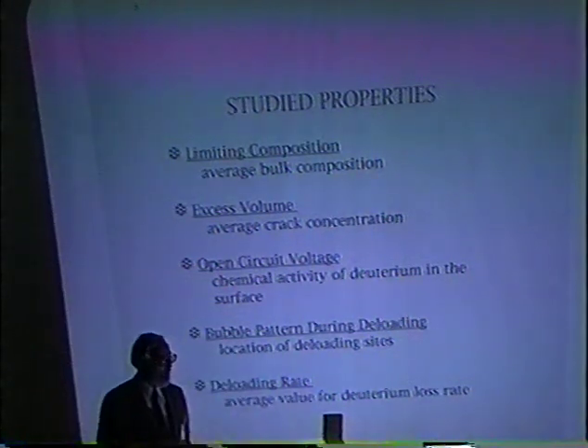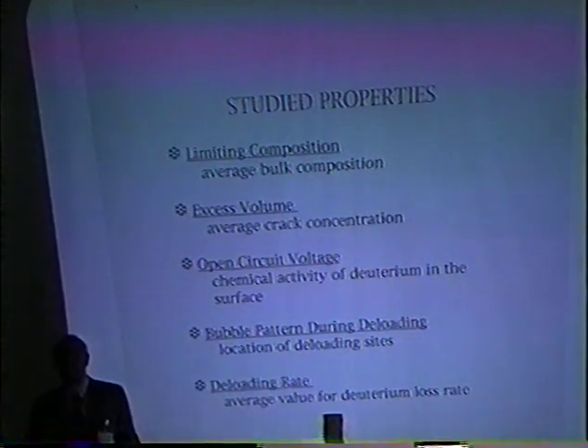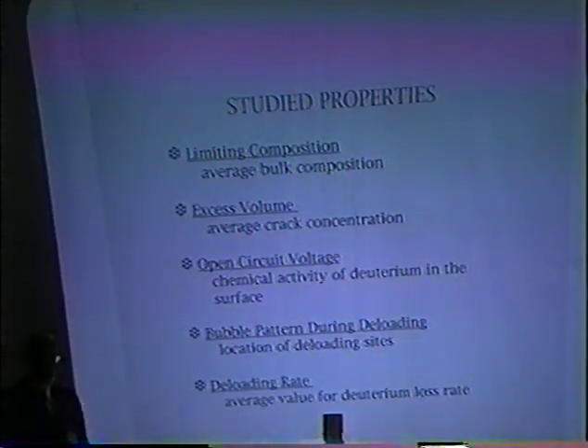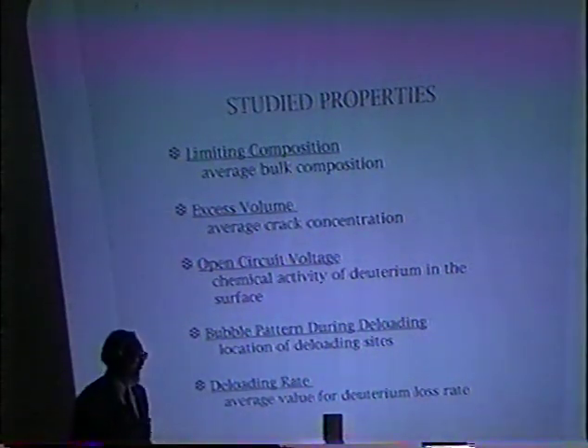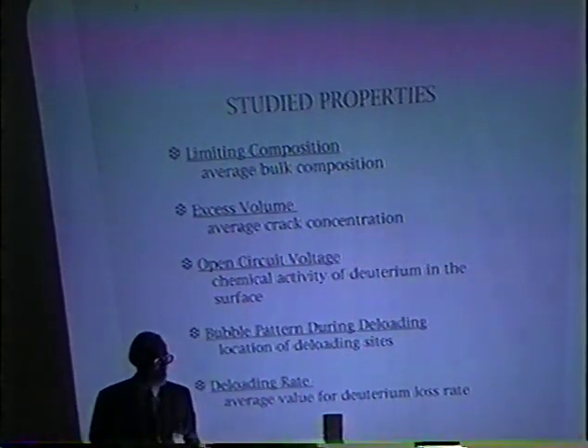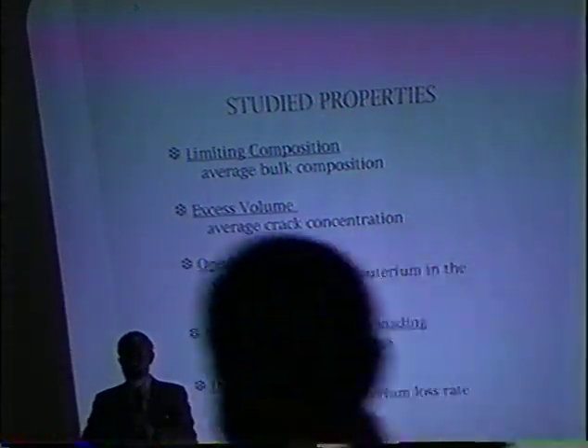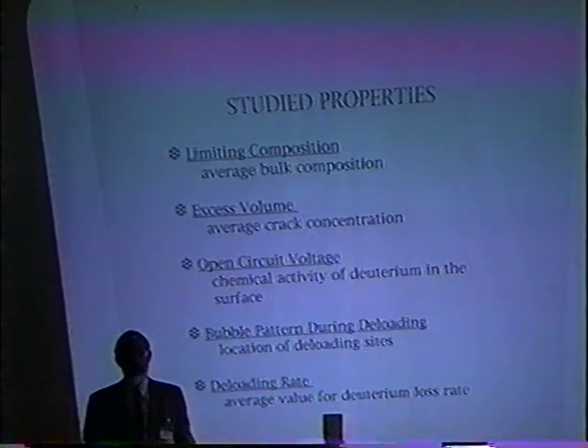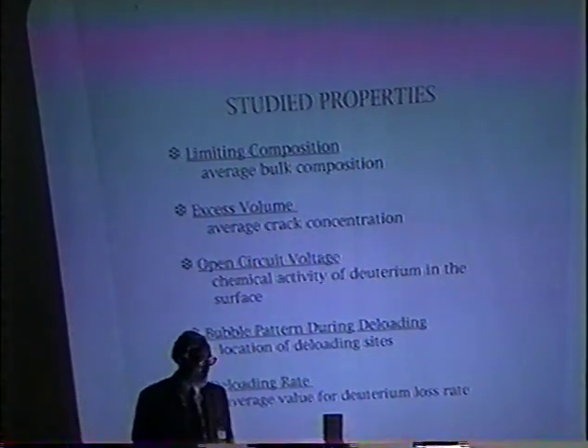The bubble pattern during deloading was looked at. This allows one to see the inhomogeneity. If you take a piece of palladium and put it under acetone and look at it with a microscope, you can see the bubbles come off. You can see the cracks, the lines of bubbles. You won't necessarily be able to see anything there from which they're coming, but they're nevertheless coming out. There's a variety of structures from which the bubbles come. But frequently there are regions on the piece from which there are no bubbles. And I believe that that's the region where most of the activity, the nuclear activity, is taking place, hopefully.